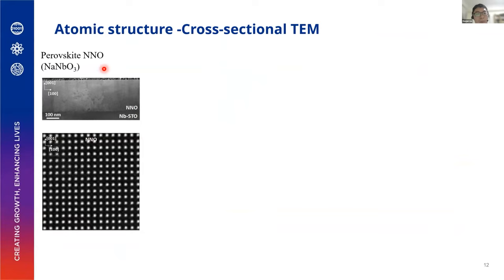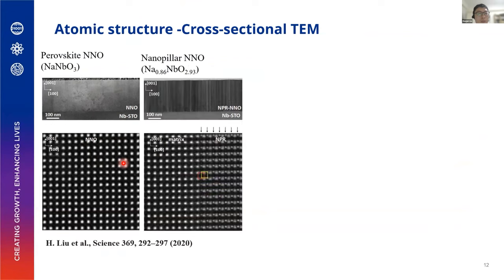In our work, we grow this film on a strontium titanate substrate, an STO single crystal substrate. This is a film with close to stoichiometric sodium niobate. This is a lattice from TEM images, which is a very typical perovskite lattice. In the case where we reduce the sodium concentration, you can form a self-assembled nanopillar structure. And this is a detailed atomic resolution image. It looks like you have another set of lattice, which is shifted vertically and horizontally.